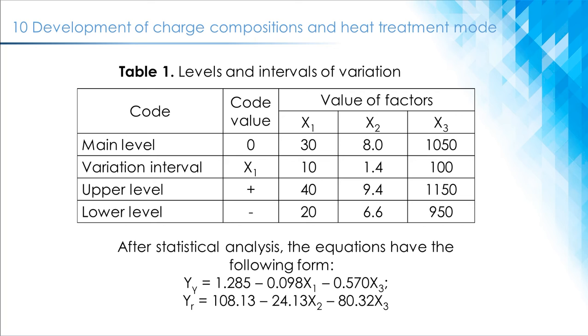Since firing for more than 10 minutes did not significantly affect the parameters under study, the firing time of the granules was 10 minutes and was not taken as a variable. The levels and intervals of variation of the selected factors are shown in Table 1. After statistical analysis, the equations have the following form. When checking the suitability of the above equations by Fisher's criterion, they all became adequate.